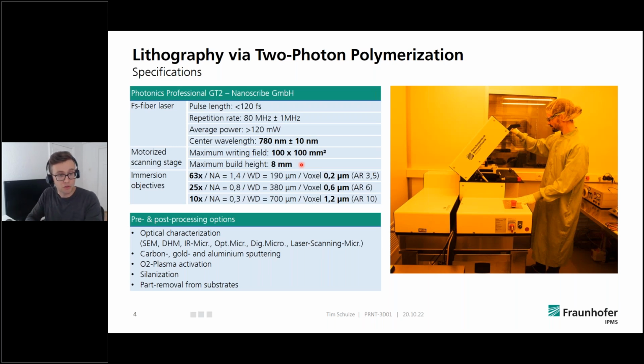In our institute, we have 3 different objectives we are using for our components, and depending on the size, you could either use an objective with a really high numerical aperture and a really small voxel, or a big voxel in the case of the tenfold magnification objective. It's a trade-off between printing time and structural resolution, and then you decide which objective you go with. What I indicated here is the aspect ratio. For instance, the voxel for the tenfold objective has a lateral width of approximately 1.2 micrometers, but the aspect ratio is 10.